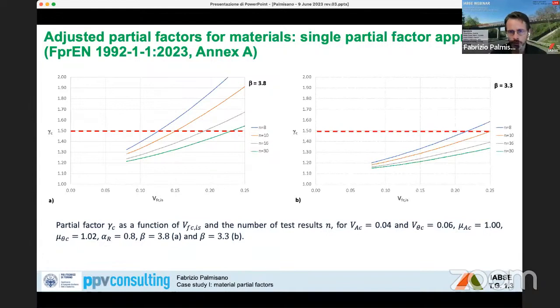It is worth noting also the great influence that the target reliability index has on this evaluation. In fact, for example, if we pass from beta 3.8, which is more valid, let's say, for a 50-year reference period for a new structure, to beta 3.3 for an existing structure, there is a strong reduction in the material partial factor. And as we can see, in many cases, also for a coefficient of variation of about 0.2, the material partial factor for concrete is lower than the one that we assume for new structures.